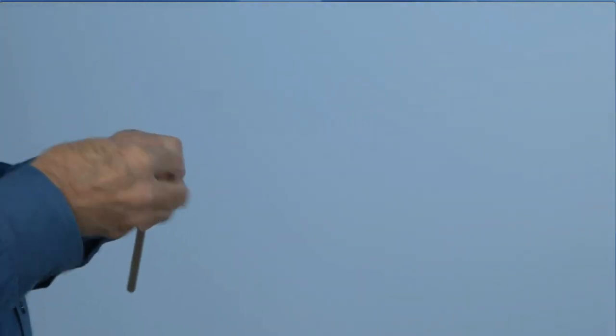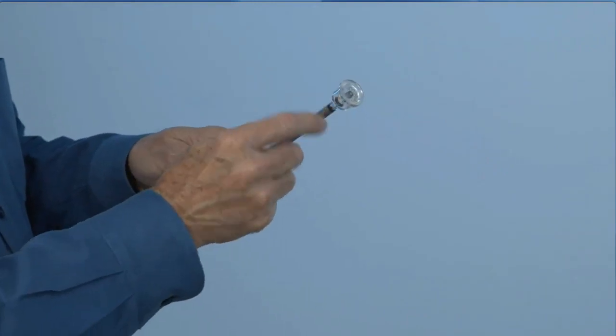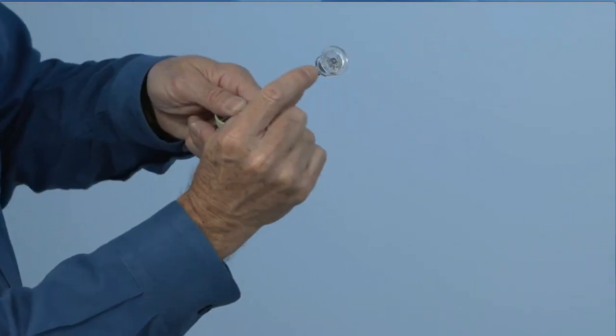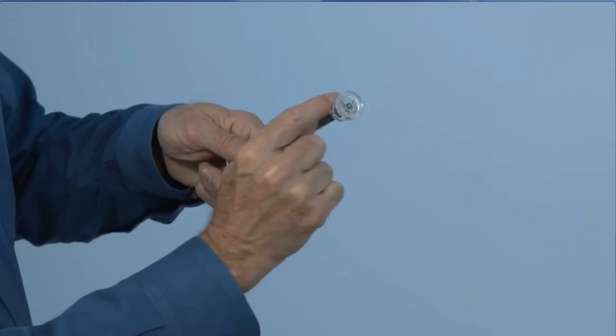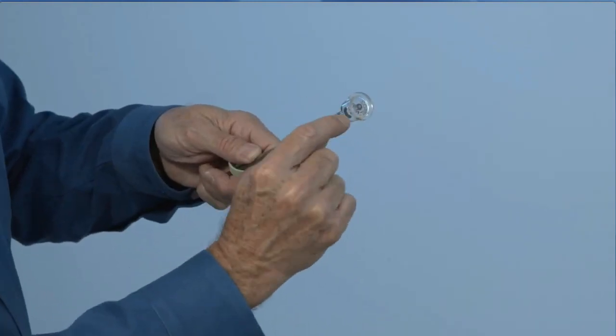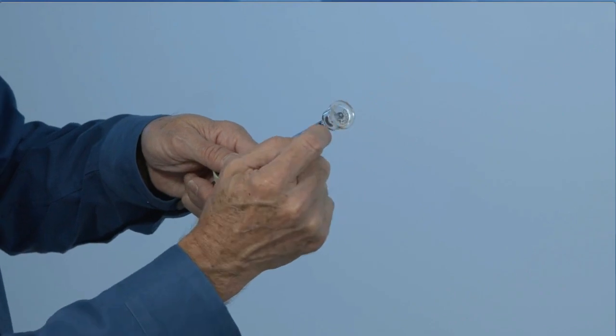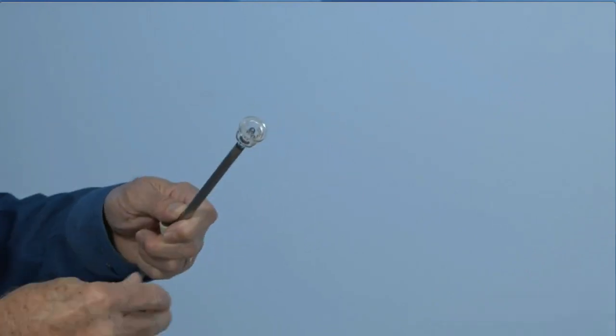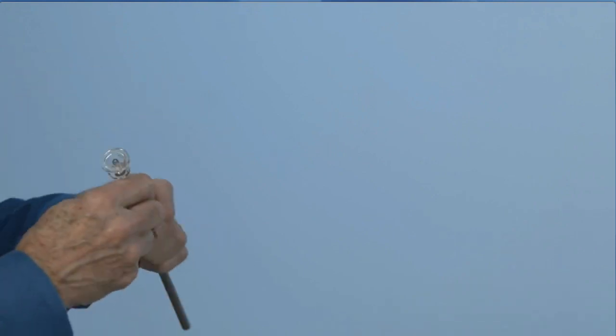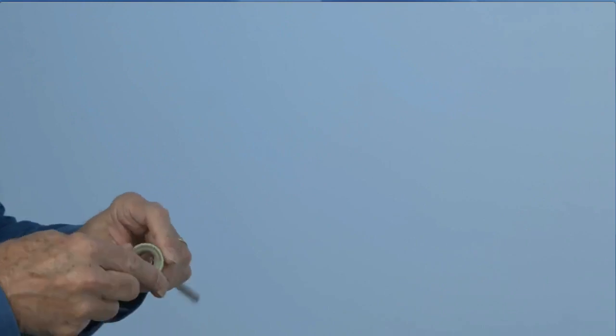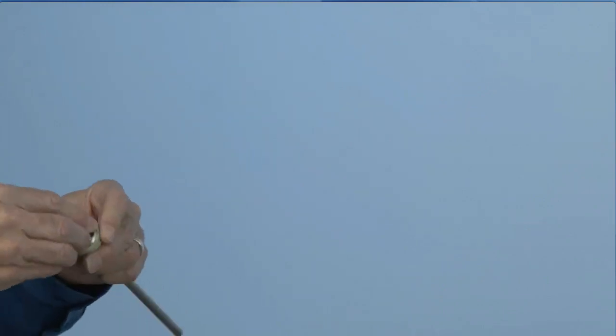If we're working with powders, we don't want the powders to be aspirated during our evacuation process. So working with the powders, and this one has a 3 cubic centimeter volume, you'll see this little stem is extending past the capillary here. That's so that we can load the powder in the bottom down here. Evacuation takes place up here, and it helps to keep sample from being aspirated. This one has a larger stem capacity than the one here did. So if we have a sample that's small in size but has significant pore volume, we've got a little more mercury to use for the analysis.